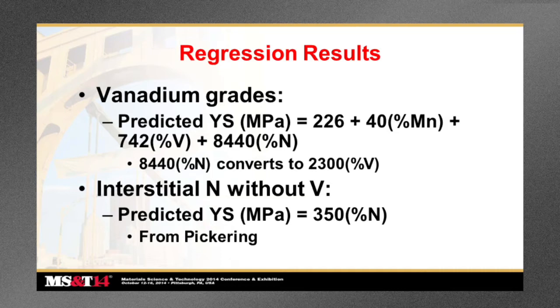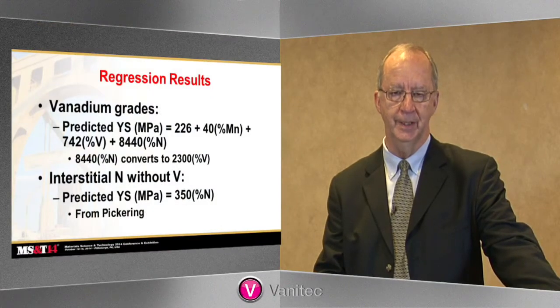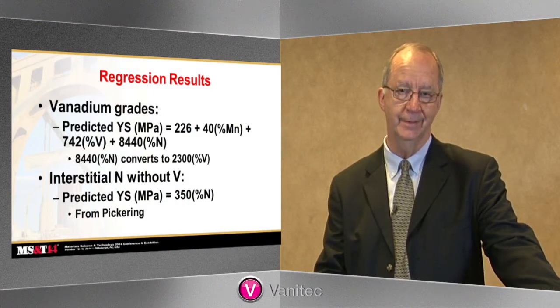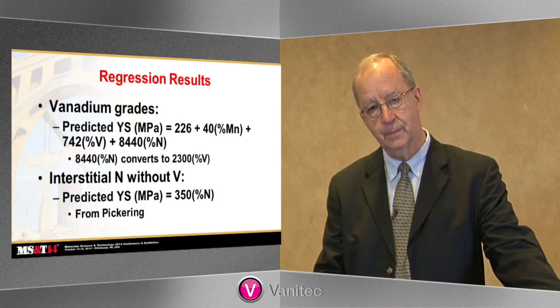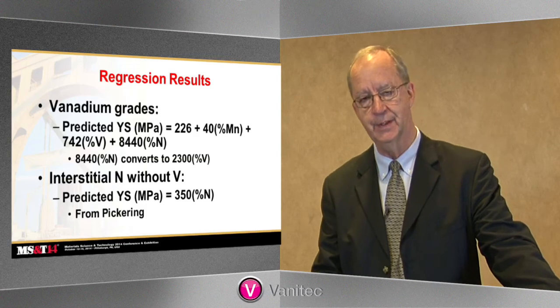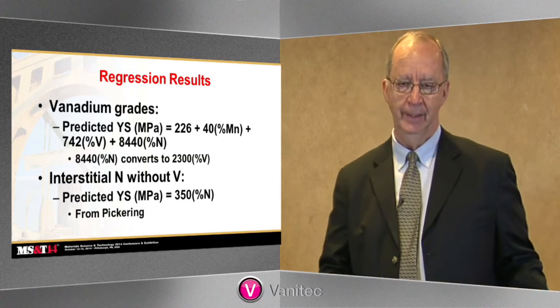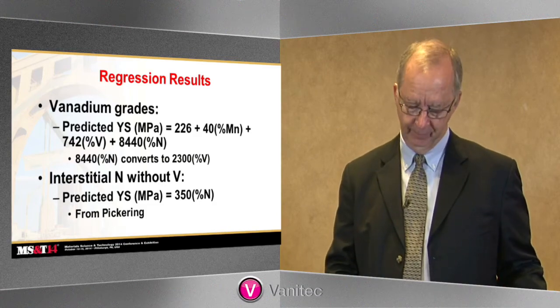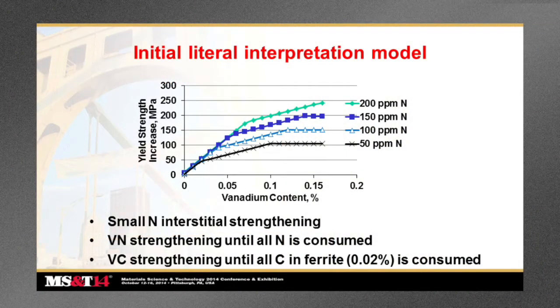You also had to develop some prediction of what the effect of interstitial nitrogen might be without precipitation. In other words, if you have nitrogen without vanadium, what kind of strengthening could you get? We used the model that was suggested by Pickering, as you see here. I think subsequent to this, there is strong evidence that says that model probably underpredicts the interstitial nitrogen strengthening component, but interstitial nitrogen strengthening is not something normally would be recommended, and so it's not a major issue with the predictive model.